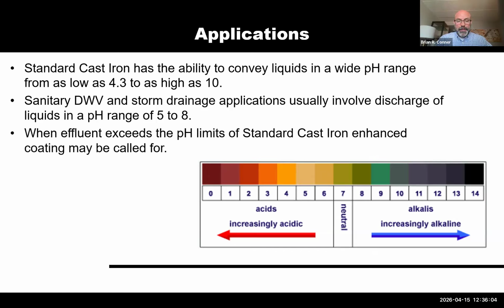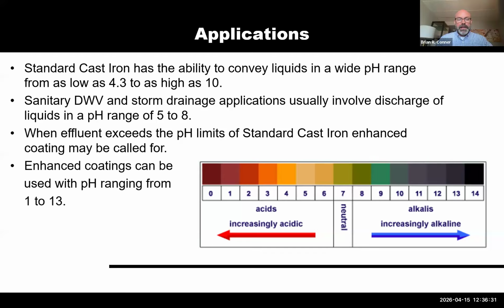Now, when these effluents and the pH limits of standard cast iron are exceeded, there are enhanced coated cast irons now. From Charlotte Pipe, we manufacture a product that's called Edge HP. The HP is for high performance, and it's a little bit of a play on the pH levels as well. So whereas normal cast iron can handle a pH range from 4.3 to 10, our enhanced coated cast iron can handle a pH range of 1 to 13. So on the pH scale is many, many orders of magnitude above what standard iron can handle.